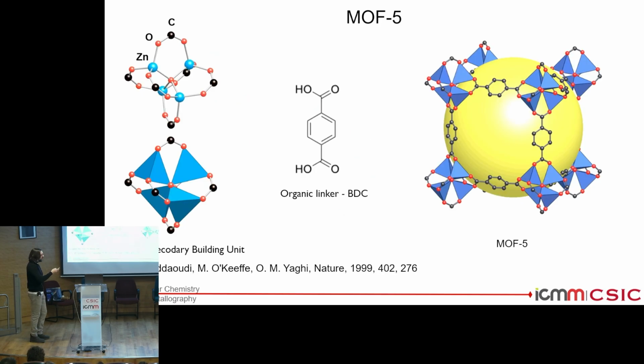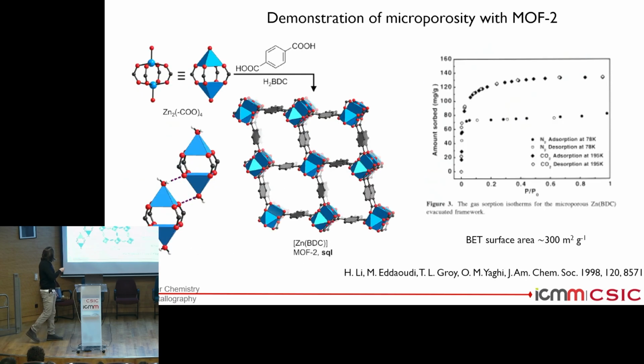So, anyways, in 1998, this paper came out from the group of Yaghi. He continued with the same carboxylic linkers, and now MOF-2 was the first material that was reported to have microporous behavior. Now, this is another demonstration of porosity, but this is also very relevant because it is made in the low pressure regime. So this is a sorption isotherm. This is the first sorption isotherm reported for a MOF.